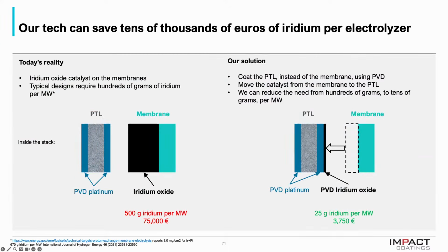Today's reality, what you find in commercial stacks on the market today, is that you have the iridium oxide catalyst on the so-called membrane. This works, but it comes with a huge challenge. The typical designs require hundreds of grams of iridium per megawatt. Inside the stack, you have the porous transport layer. This is normally coated with platinum, and you have the membrane with a very, very thick iridium oxide layer. To put some numbers to it, 500 grams of iridium is about 75,000 euros. Iridium is very, very expensive, and it is limited in supply. So this really is a bottleneck.